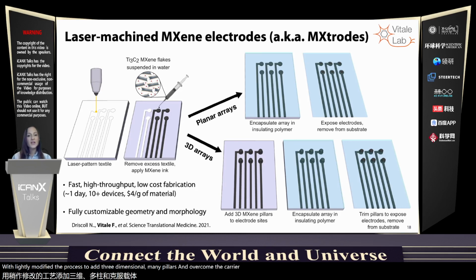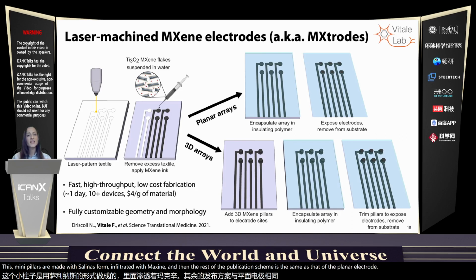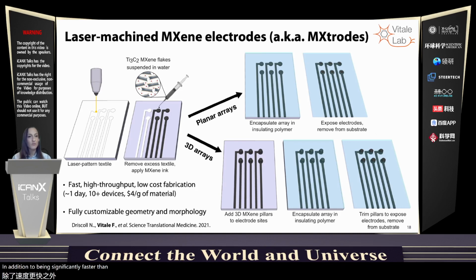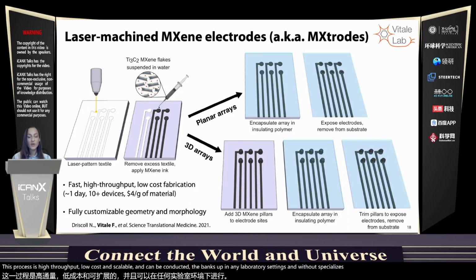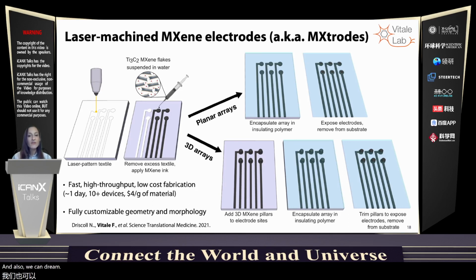These mini pillars are made with cellulose foam infiltrated with MXene, and then the rest of the fabrication scheme is the same as that of the planar electrodes. In addition to being significantly faster than microfabrication, this process is high throughput, low cost, and scalable, and can be conducted at benchtop in any laboratory settings and without specialized equipment. And also, we can really fully customize the shape, size, and geometry of our devices.